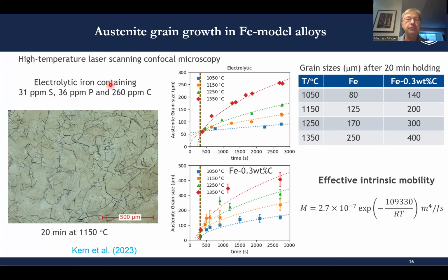And they started off with electrolytic iron that contains sulfur, phosphorus, and carbon as trace elements or residuals, if you want, on the ppm level. And they were very excited about their results. They found parabolic grain growth, and this was representative in the first look for grain growth in pure iron.